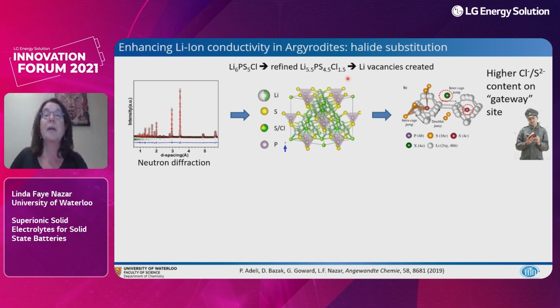And so we simply did that by achieving materials that are chlorine rich by fairly simple techniques. And we also increased, of course, the amount of lithium vacancy. So this is kind of the opposite to stuffing the structure.